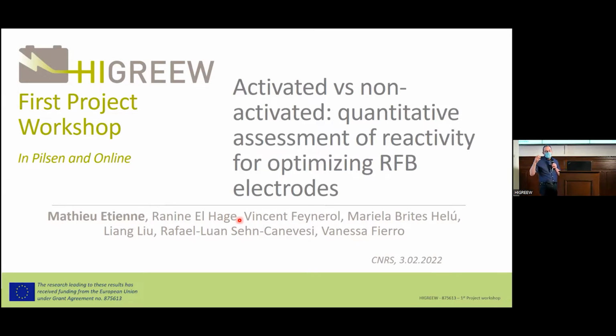This electron transfer reaction is a basic reaction that allows electrons to be transferred with the electrolyte in the solution. It's a critical reaction, because if we have low kinetics, we are losing some of the energy during the charge and the discharge. So the first objective is to reach this 10 to the minus 3 centimeter per second, and the second objective is to reach a certain cost, less than 100 euro per square meter of the material.